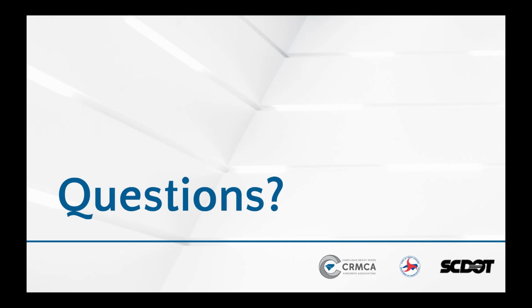The problem with maturity is you do it during the mix design process where you establish the relationship, but if the mix proportions change in the field, or let's say the cement source changes, or the fly ash changes, or whatever, the correlation between your lab-derived relationship and what is happening in the field is lost. So it's a good intermediate step, but what we find to be better is moving towards match curing, where we would cure our cylinders in a match cure environment. Then if we need to drill holes, tilt it, or load it in some way, we break a cylinder when we believe it's there, but we know that cylinder matches the strength in the field. So it's better than not doing maturity, but it does have limitations.